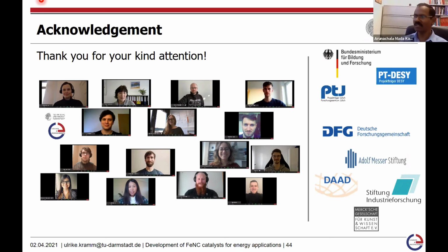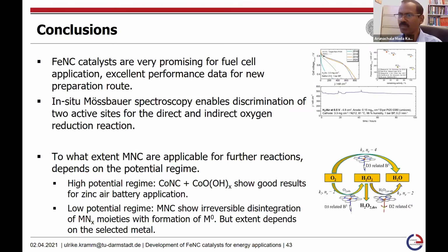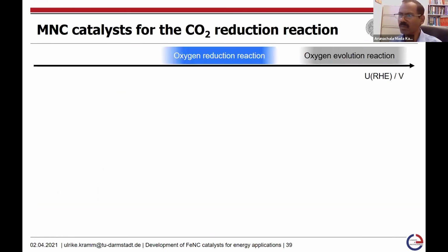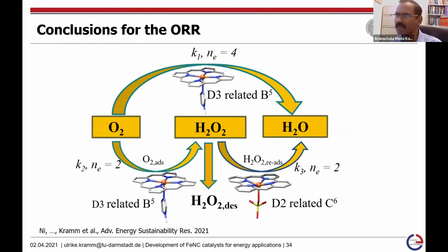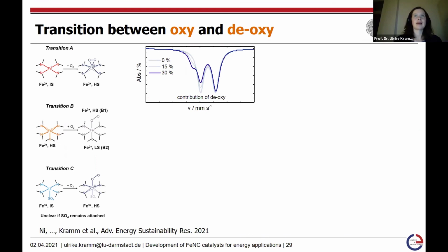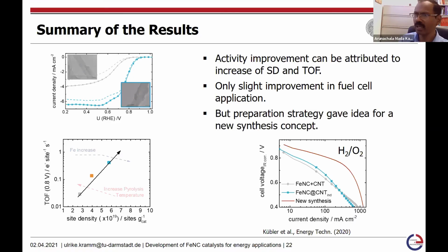Well, nice presentation. It was very insightful how the non-platinum catalyst for oxygen reduction in the PEM fuel cells. I was looking at one of the slides where you had the fuel cell polarization data, that the OCV was only about 0.9 volt, even though you used hydrogen and oxygen gases as the feed. I guess you mean, just give me a second. You mean this hydrogen and oxygen one? Yeah, I think that's the one on the right-hand side bottom. So what is the reason for the lower OCV, even though you used hydrogen and oxygen, typically it is always above 1 volt?